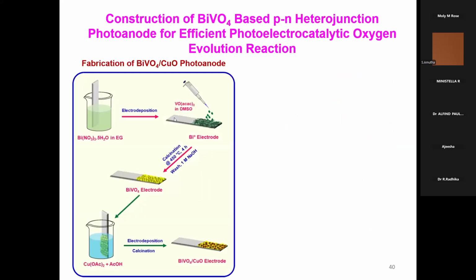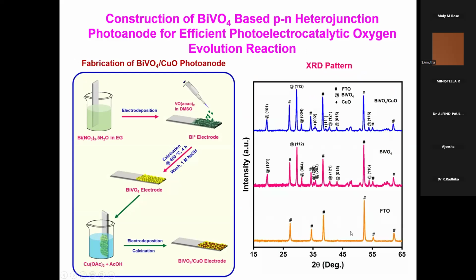Here we have made a bismuth vanadate and copper oxide heterojunction for photoelectrocatalytic water splitting. For that, initially we did electrodeposition of the bismuth-based material. Then it was subjected to electrodeposition with copper acetate in acetic acid. Followed by calcination, it forms the bismuth vanadate and copper oxide heterojunction. So just look at this. This is the reference pattern of the FTO. This is after deposition of the bismuth vanadate. Here you can see the signature peaks due to the bismuth vanadate.